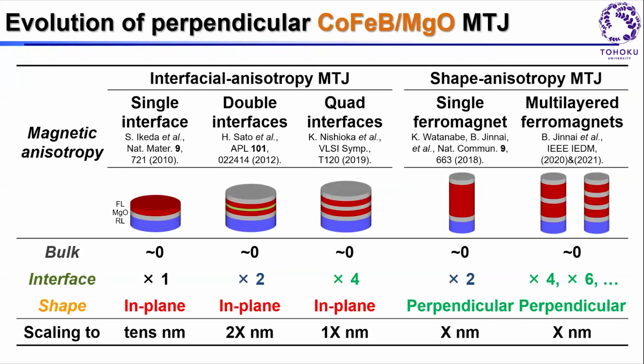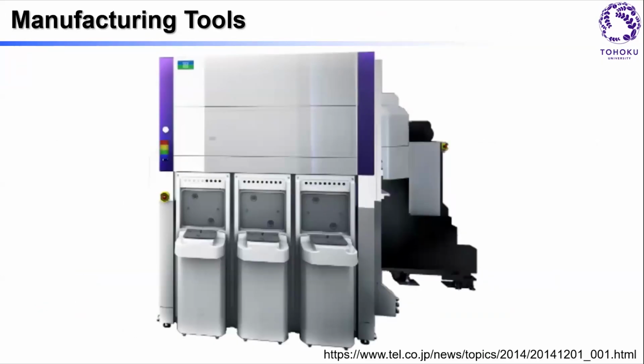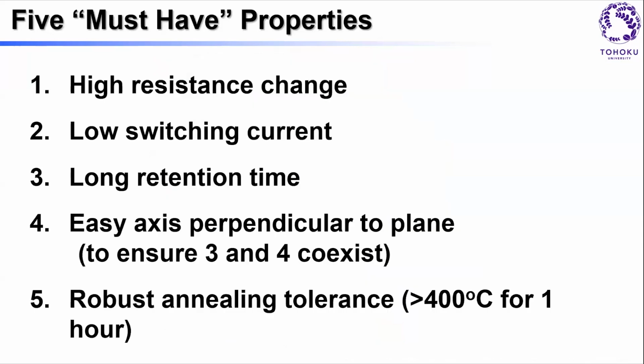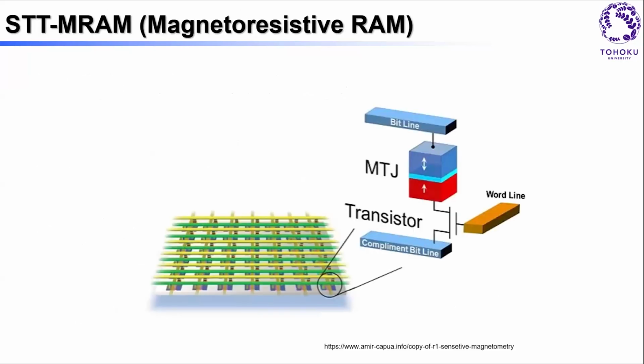So this is a spectrum of the magnetic tunnel junctions that we have placed. And here, these are commercially available. We have to develop, or people have to develop, processing technology as well. But the good news is that the materials you use for the whole spectrum are basically the same, and you don't have to change them going from generation to the next generation. Otherwise you have to add a new material system. That's always a nightmare, but you don't have to worry about that until you hit the very end of the 3 nanometer scale.